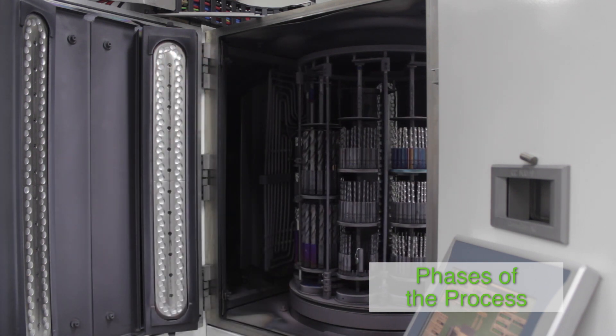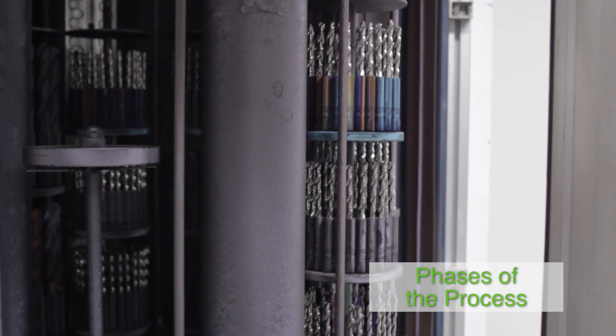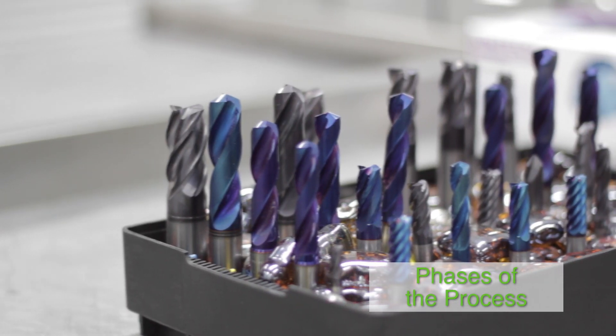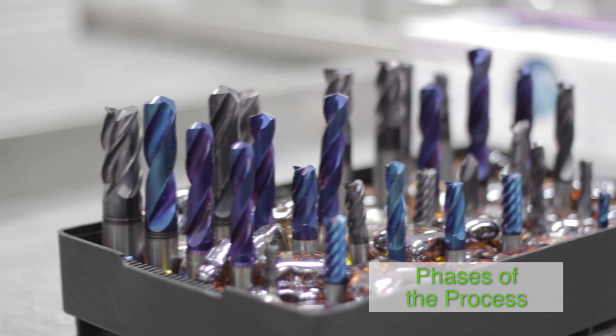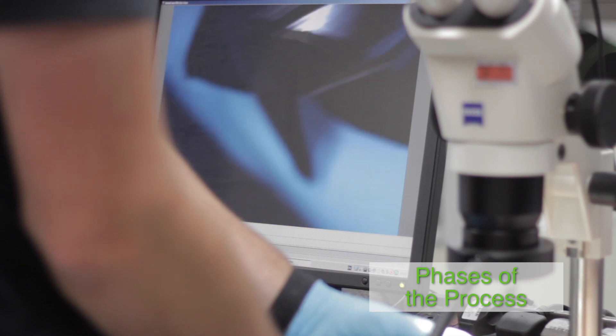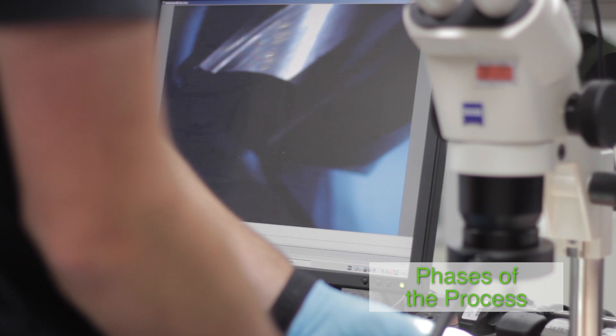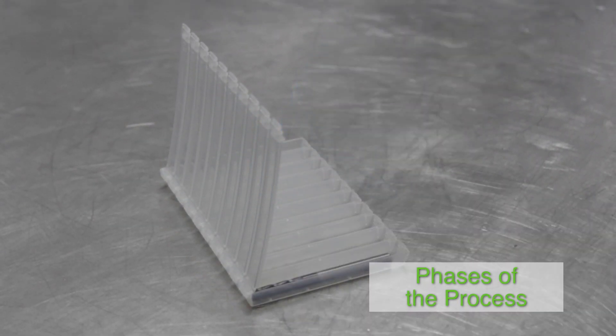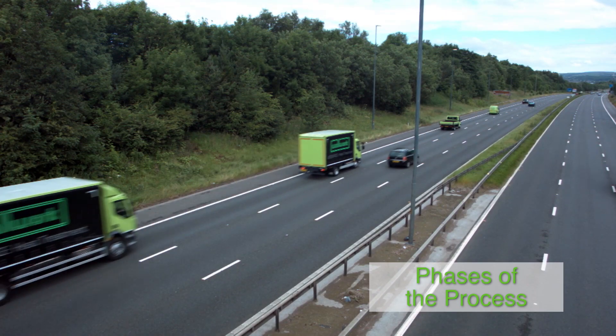To provide a final improvement step, the coated tool can be re-honed using fine-grain aluminium oxide. The super-smoothing further enhances chip removal in drilling and milling operations. The coated tools are then inspected visually using microscopic assistance. Test coupons coated with the tools are tested for key properties and retained for future investigation, utilising the test facilities in Wallwork's excellent laboratory. The quality-assured coated tools are then packed in specified packaging and transported back to the customer using Wallwork's own transport, guaranteeing security and safety of their tooling.